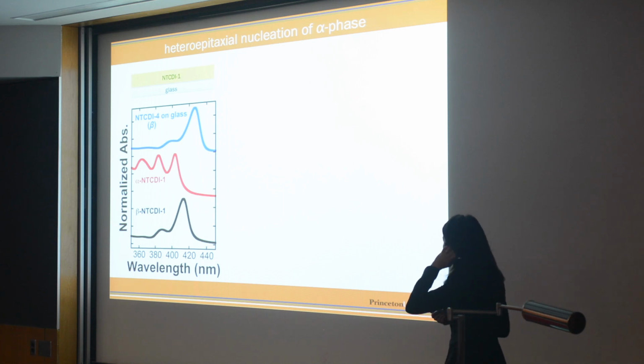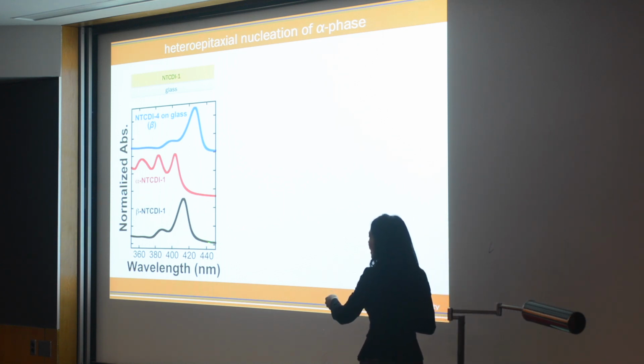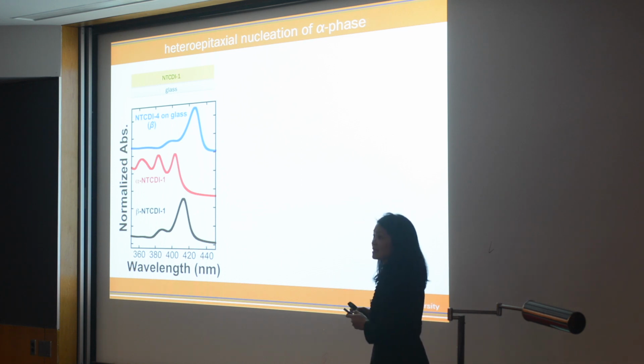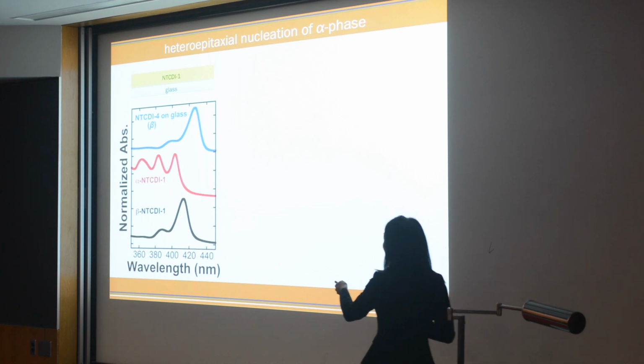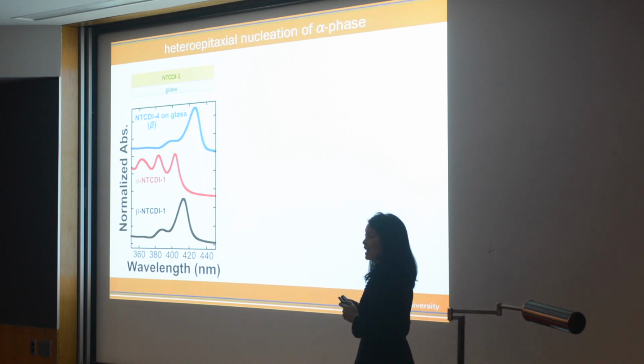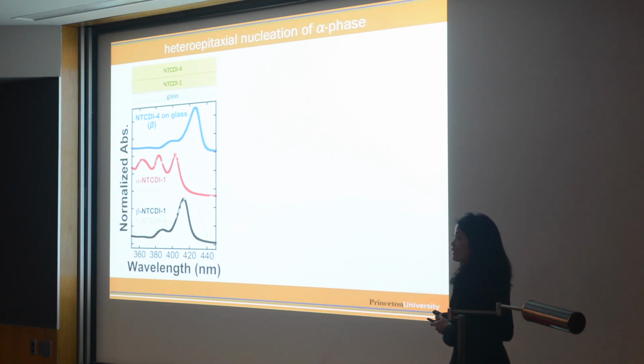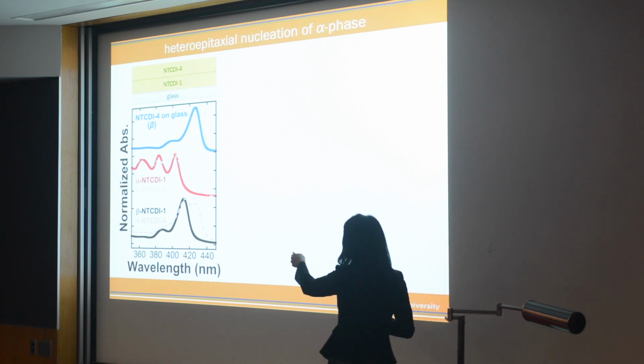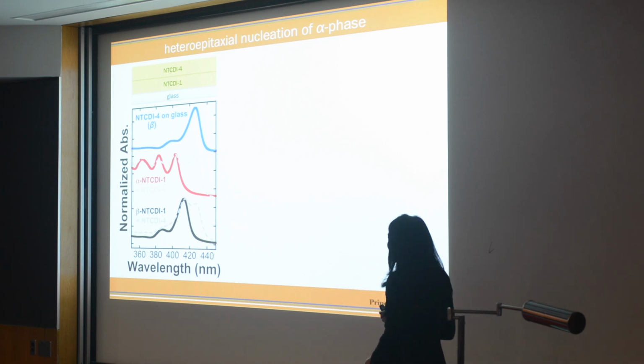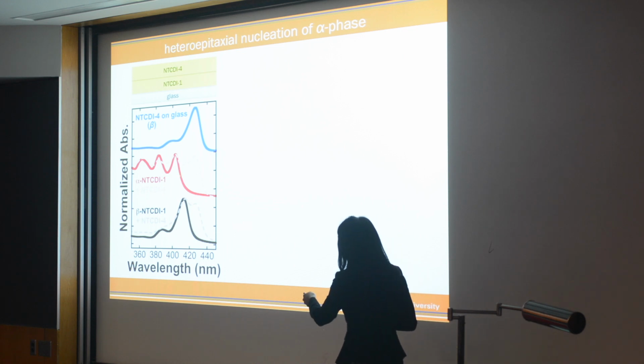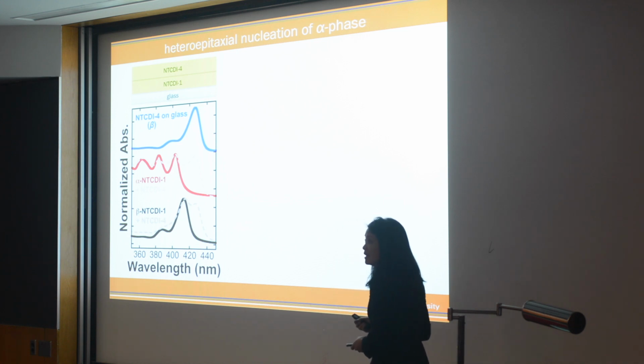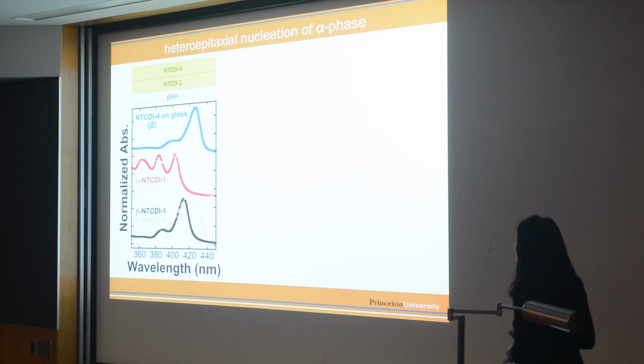So that's the data. This is the reference data. NTCDI1, the beta phase, is shown here. And then when you convert NTCDI1 to the alpha phase NTCDI1, that's its fingerprint, so very different. And this is NTCDI4 in its beta phase, which we can access. Okay? Now, when you put on NTCDI4, because UV Vis we're doing through the stack, it's a transmission experiment. So it's basically through both NTCDI1 and 4. And so that data is shown in the dashed lines here. It's not so easy to deconvolute, but you can already begin to see differences here. So here, for example, in the pink dashed line, you see intensity or absorbance that you don't see in the gray, suggesting that we do have access to this alpha NTCDI4.